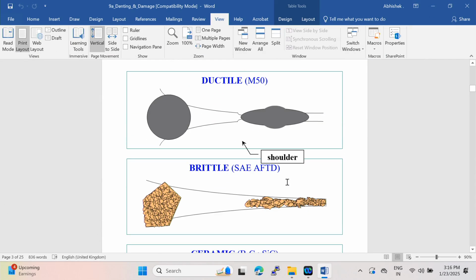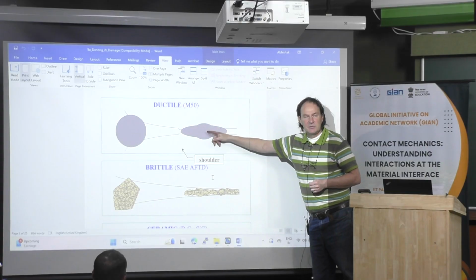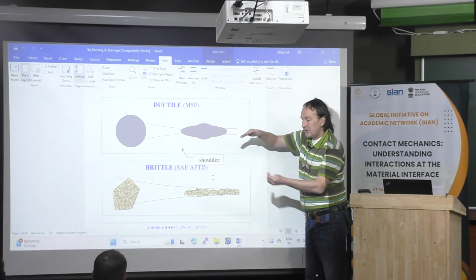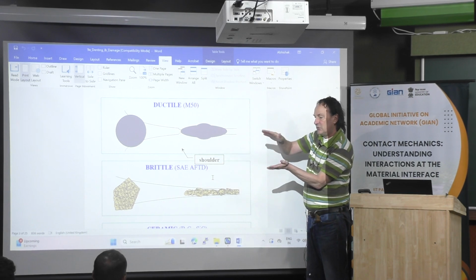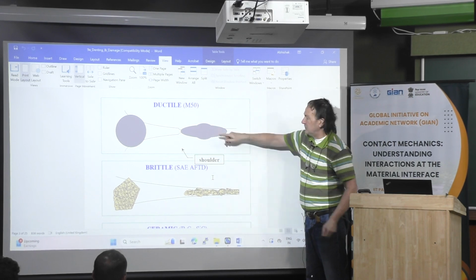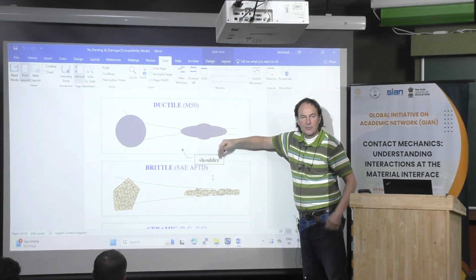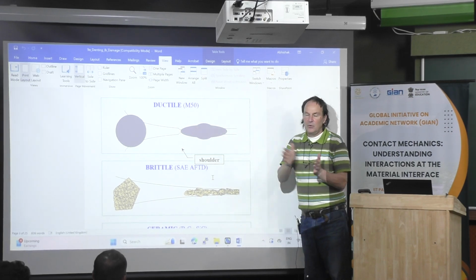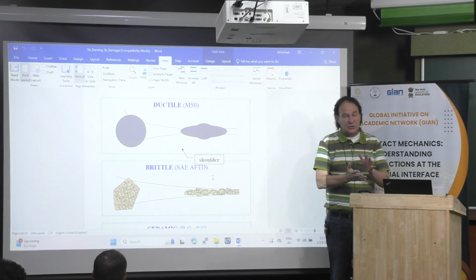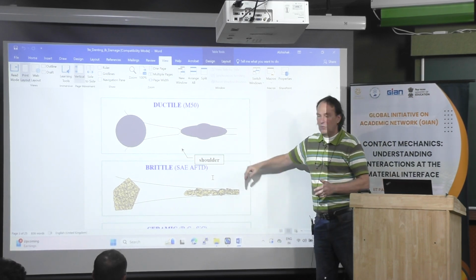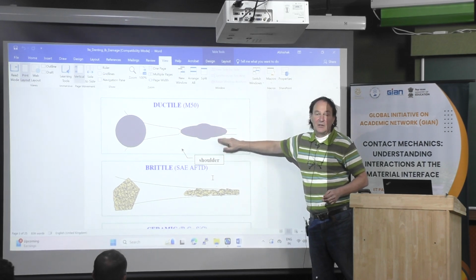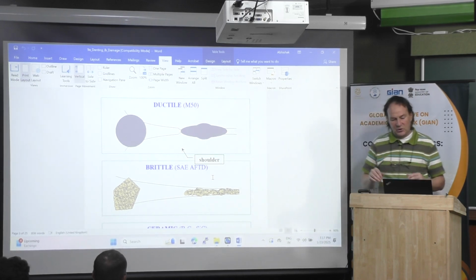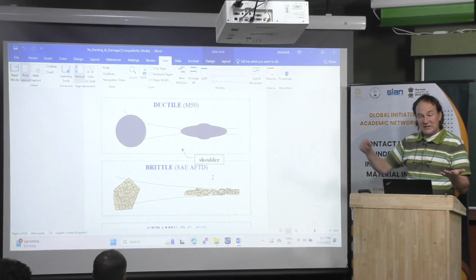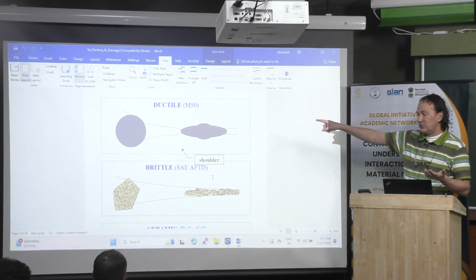Typically, these are different types of denting you can observe. The first one is for metallic particle, M50 is a bearing steel. There is a specific shape. Maybe I will explain that later, but at the beginning, in fact, you crush the particle just at the top, and after a while, you start to indent both surfaces. And after a while, because it happens very quickly, you start to heat the materials and you start to flow. Then after a while, the yield strength of the material is lower. It creates this type of shape. And we were able to see that on particles and also to measure that on the surface.